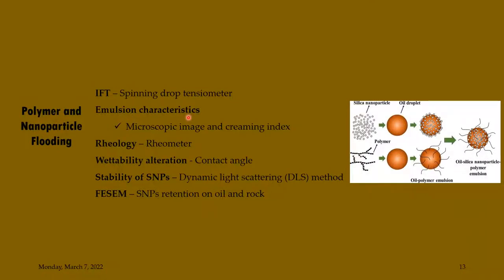polymer. So here we are trying to explore nanofluid flooding. We have taken heavy crude oil, which we are trying to compare between simple polymer flooding and polymeric nanofluid flooding. We wanted to see the properties of these nanoparticles in improving these properties, because nanoparticles have more or less the same properties as the chemical EOR, but these nanoparticles are much more effective than chemical EOR towards these mechanisms that result in higher oil recovery. And what those are is what we are going to see. So you can see here, we have measured the IFT using the spinning drop tensiometer.